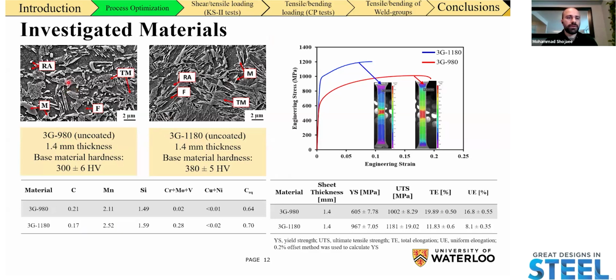You can see representative scanning electron microscope micrographs of these two steels, where we have different phases present at the microstructure, specifically the retained austenite, which I mentioned is the one responsible for the TRIP effect. And we have different volume fractions of hard and soft phases, which is characterizing the difference in the strength of these two steels. At the bottom, you can also see the chemical composition of these materials. And on the right-hand side, you can see representative standard tensile tests performed on the as-received parent metals.